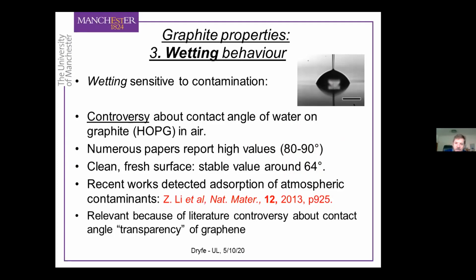And basically, it comes back to the factor I just mentioned. It's the adsorption of atmospheric contaminants, because graphite rapidly becomes contaminated with the organic junk that's around us in most urban environments. This adsorption of hydrocarbons, if you like, and other organic materials, changes the contact angle. And this was well discussed in a Nature Materials paper that came out a few years ago now. So this has been recognized as the phenomenon responsible for the change in the contact angle of graphite.